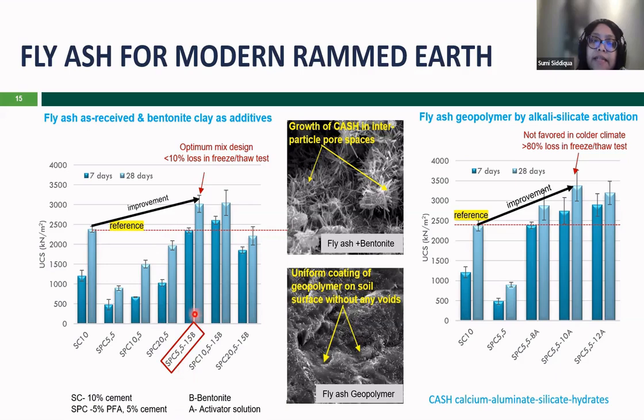Then we have 5% Portland cement, 5% fly ash, and 1.5% of the bentonite material added to that. And then we have 10% fly ash, 5% cement, and 1.5% bentonite. And then 20% fly ash, 5% cement, and 1.5% bentonite.